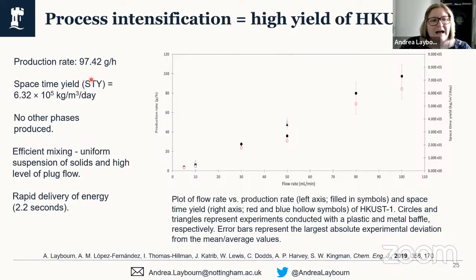We then wanted to have a look and see what our space-time yield was against other reactors. And given that our reaction takes place in a tube, the reactor is a very, very intensified process. And so we were able to show that we could get the highest space-time yields for any MOF produced to date using this particular setup. For those of you who are familiar with HKUST-1 and reactions between copper and trimesic acid in different solvents, you may be aware that other phases can potentially be produced, and we were able to show that that wasn't the case through our powder diffraction.